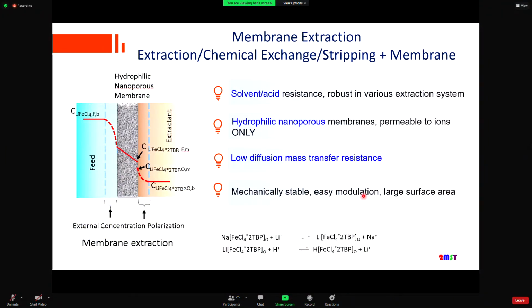What is the membrane extraction? It is so simple that when we put a membrane barrier in between brine and the organic phase, we have a membrane extraction. For this system to be stabilized, to stably operate, we need a solvent acid resistant material, which is resistant to any kind of organic extractant. We need a hydrophilic nanoporous membrane, which is permeable to ions only. We need a low diffusing mass transfer resistant membrane, as well as a mechanically stable system material.